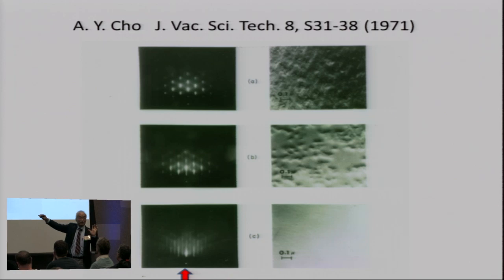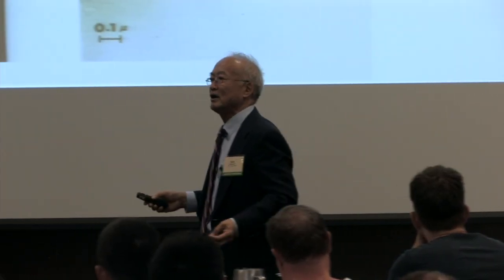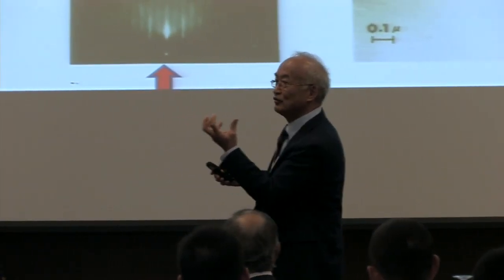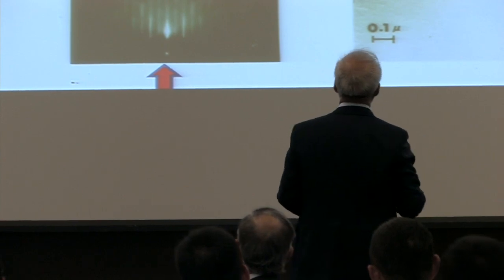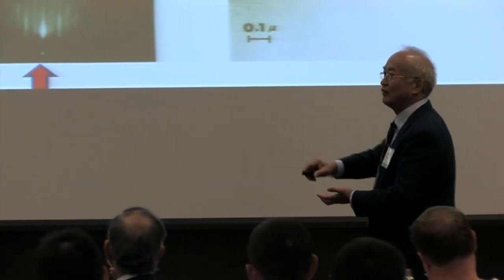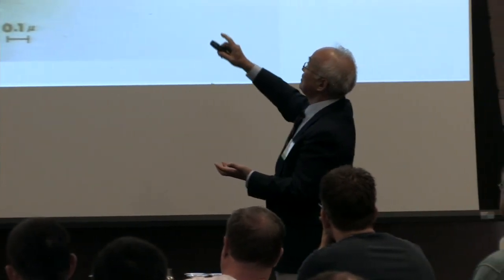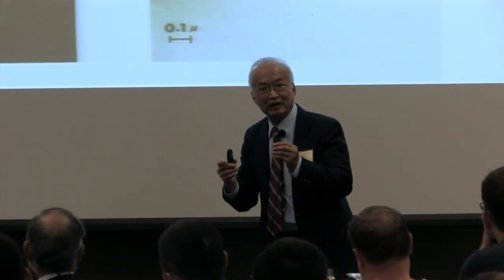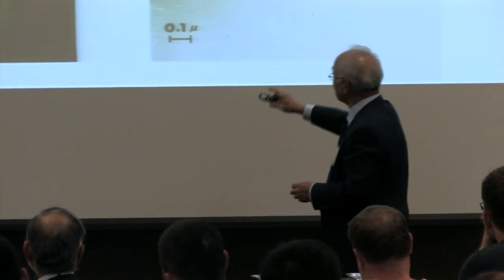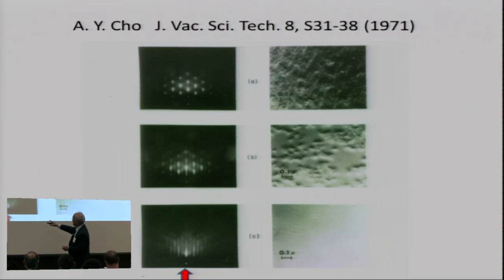The electron beam, the diffraction beam, coming onto the surface at a grazing angle, has to penetrate through the protuberances on the surface. The three-dimensional Laue condition has to be satisfied, and it gives you spot diffraction in reciprocal space. Now, when I grow with MBE on the surface, it forms larger, smoother areas. And you see here, in the second one, the diffraction pattern getting a little bit more streaky. And then finally, it gets so smooth, atomically smooth, that the diffraction pattern becomes strictly streaks. Why? Because with the two-dimensional Laue condition there are reciprocal rods, and the Ewald sphere intersects the reciprocal rods at the zero point, giving lines.